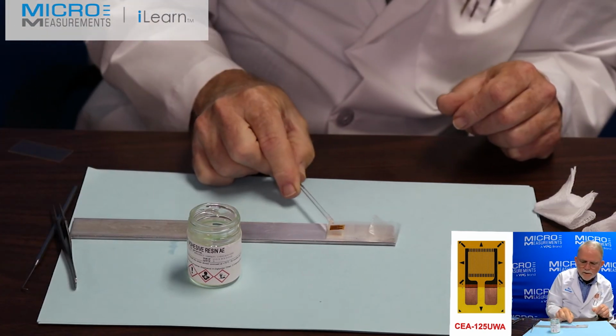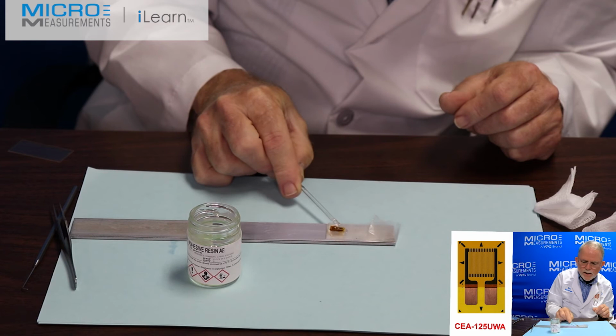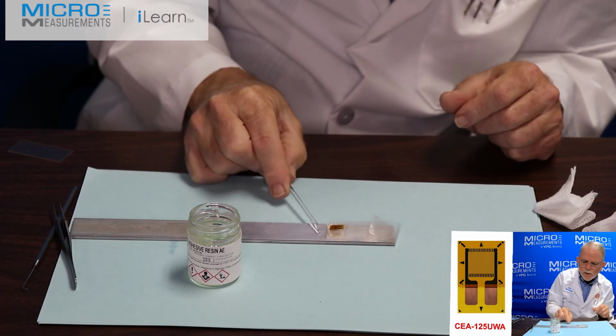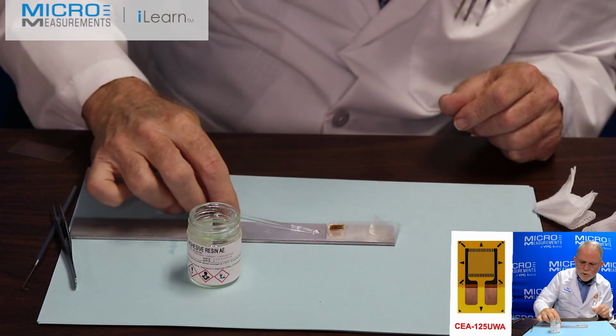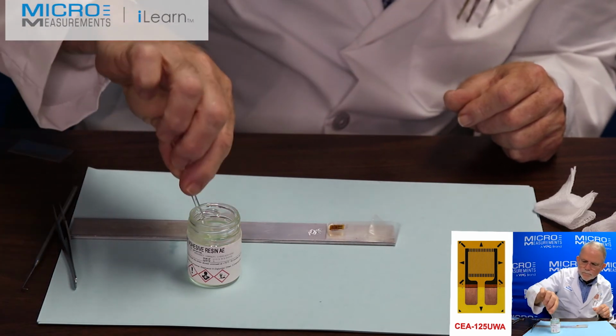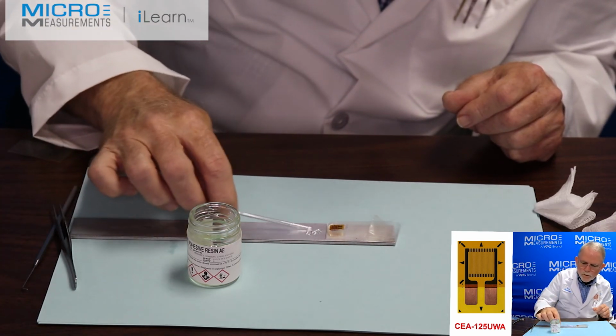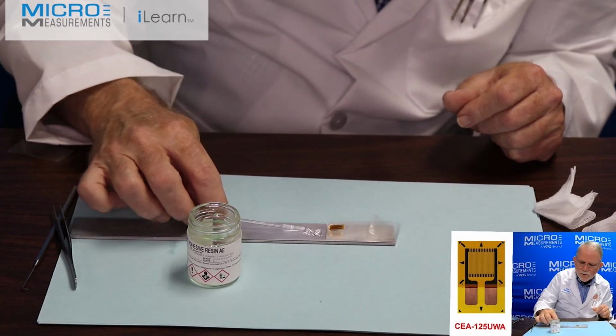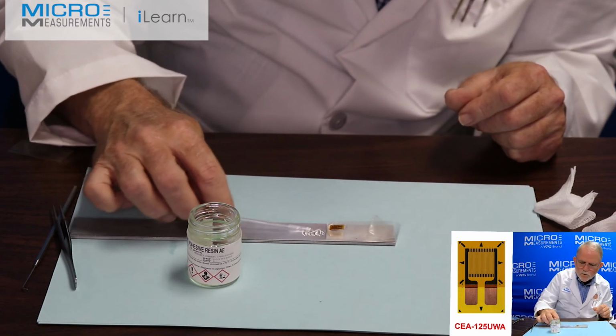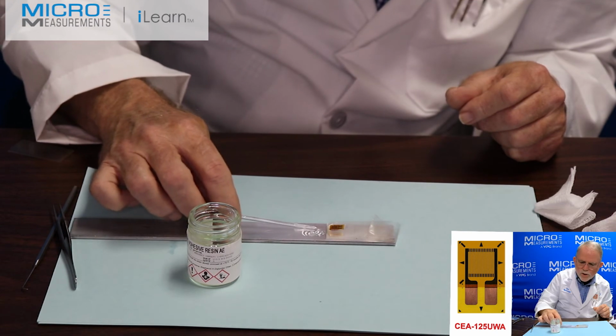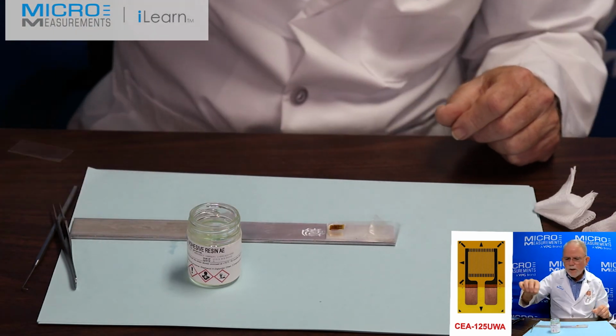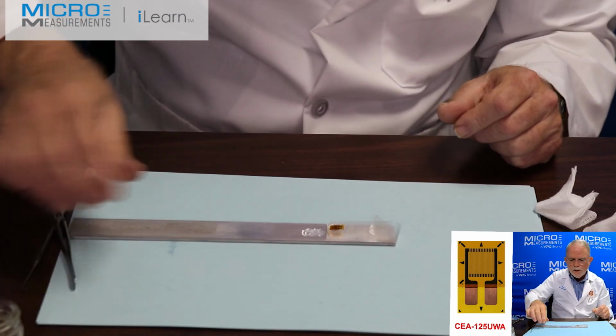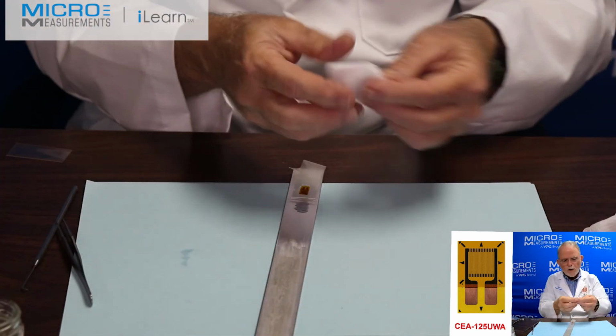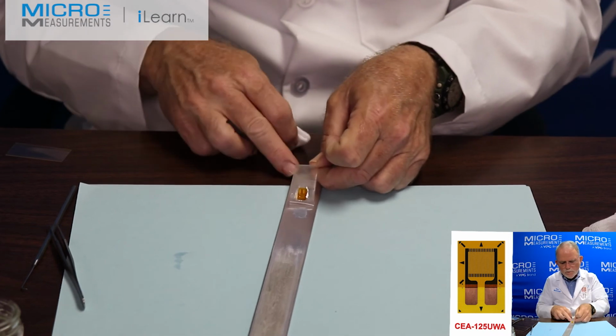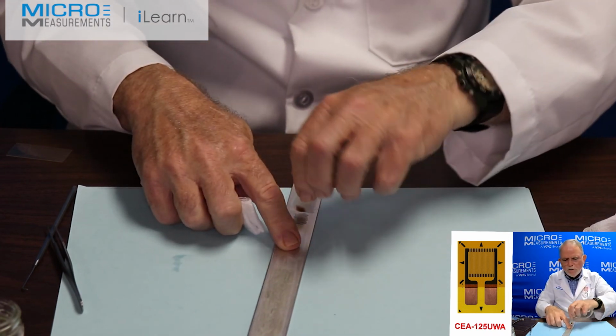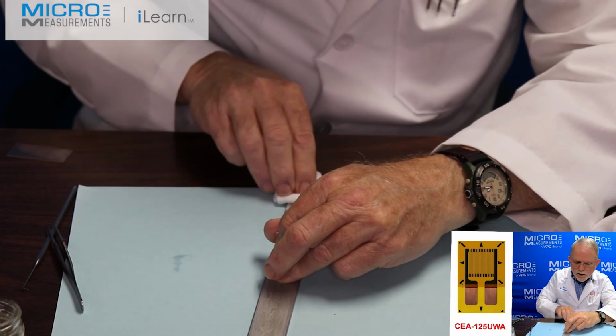Then I'm going to wet the surface of the gauge and also wet the surface of the beam where the gauge is going to land. Just a little bit of adhesive where it's going to land. This way we ensure that we don't have a starved bond line. Having done that, I'm now going to take that clean, dry gauze sponge that I folded into quarters. I'm going to squeegee through the adhesive,